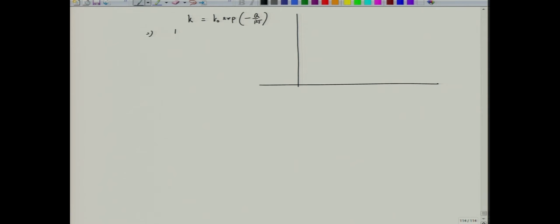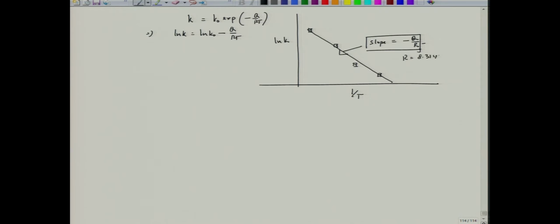So, now I can write ln k = ln k0 minus Q by RT. So, I can plot ln k at 4 temperatures, I will get these 4 data points, and then I can do a linear approximation, and after doing that I will get the slope, which will be nothing but Q by R. R we know, R is nothing but 8.314 joule per Kelvin per mole. So, once we know this, I can find out Q, which is nothing but the activation energy for the oxidation process, fine.